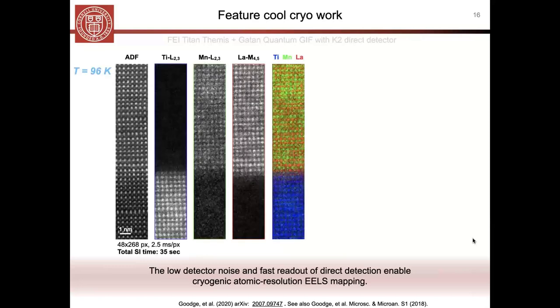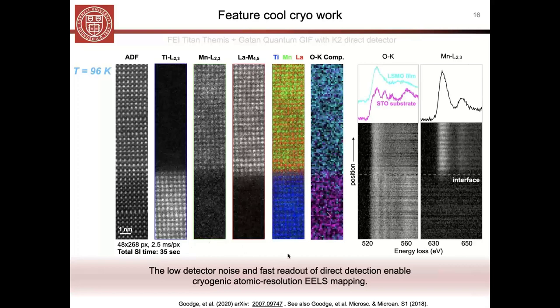And so that's actually what we've been able to demonstrate, some very cool EELS work, if you pardon the pun, which is two-dimensional atomic resolution mapping at cryogenic conditions. And so here you can see this same interface with a total SI time, again, of much less than a minute, which is very fast for folks who know EELS. And so, as I already pointed out at the introduction, we want to actually go beyond just the elemental mapping, and we want to also start to extract chemical information. And so we can even do that.